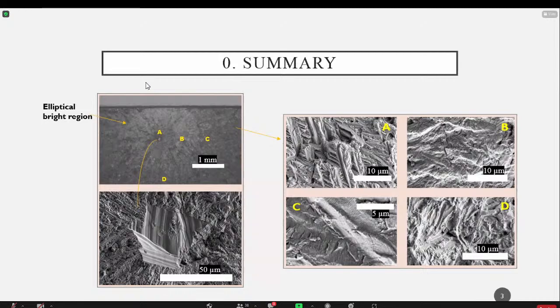So you can imagine the complete evolution of the crack as emanating at the periphery of this internal defect, then growing in an internal elliptical way until it touches the free surface of the specimen. Then it becomes a superficial crack and keeps growing until it reaches the final failure. In all that evolving process, we saw 4 different regions in this fracture surface.